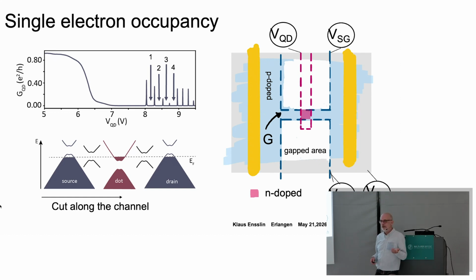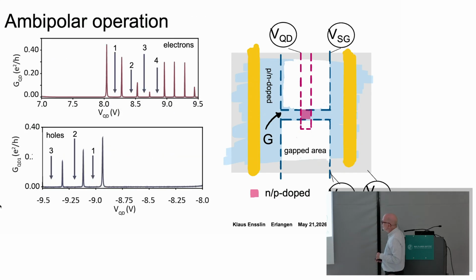Now what you can do is you can, of course, invert all of those gate voltages. And in the very same sample, you can fill in holes. And now you have 1, 2, 3, 4 holes and so forth on the other side. And you can actually build a device that has two dots, one containing electrons and the other one holes. That's something you cannot do in any other semiconductor. But you can do it here because the band gap itself is just a little larger than all the other energy scales in the system.